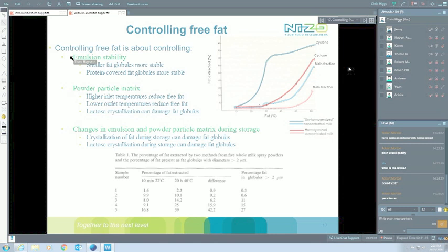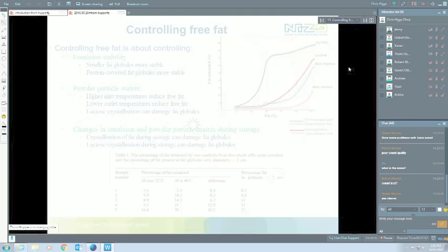And I mean, just to look at an example, what you typically see, cyclone powders, so the smaller powder particles in milk powder, whether it's from unhomogenized or from homogenized milk, tend to have a lot more extractable fat, free fat in there, than we would have in the main fraction of the powder. So again, if we're going to get a lot of fines, if we're going to get very small particle sizes in the dryer, we also run a risk of high free fat on the powders.